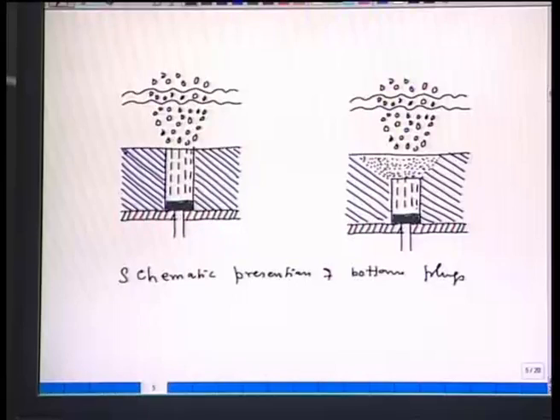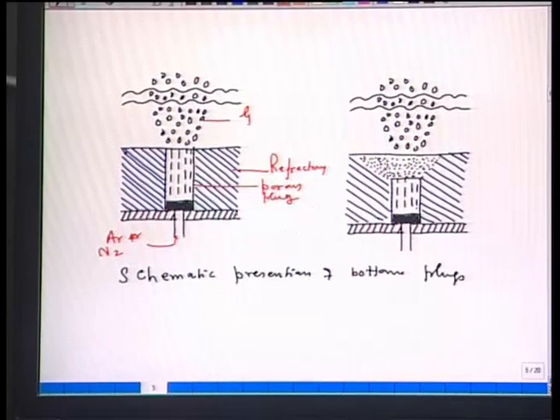I could get 2 designs of the plug from the literature, but there could be many more. You may think of some other design, because ultimately it has to work in place. Now, in one design, this is the refractory lining, this is the refractory, and this is the porous plug. Here you put argon or nitrogen. These are the gas bubbles. This is slag, and naturally these are the bubbles that are going out.